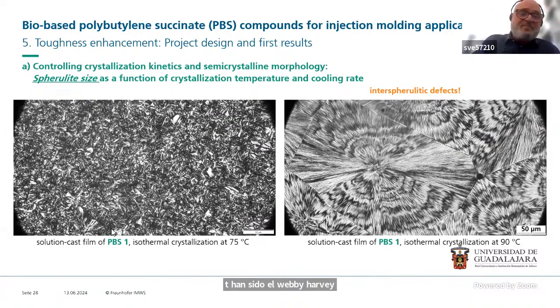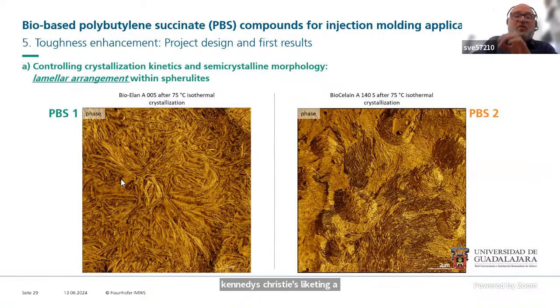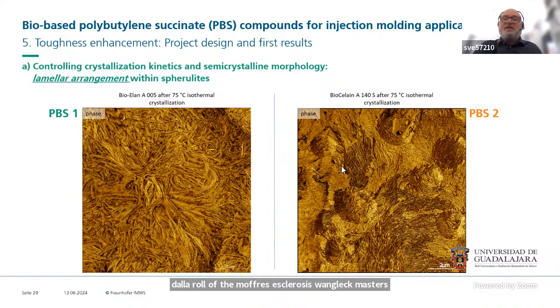So the aim must be to come here to a beautiful, fine spherulitic texture that is favorable with respect to the mechanical properties. So we have to control the crystallization kinetics, crystallization temperature, cooling rate, and so on. Of course, we can also have a look at the lamellar arrangement. The lamellar structures that you can see here in the AFM pictures also play a role. Here, especially, we have to consider the arrangement, if the lamellae are parallel, if they are packed in a way like shown over here. And we have to consider the role of the amorphous, non-crystalline part between the lamellae, because that is what is transmitting the toughness, what is giving the connection between the crystalline areas. So one look must also go to the lamellar morphology of our system.